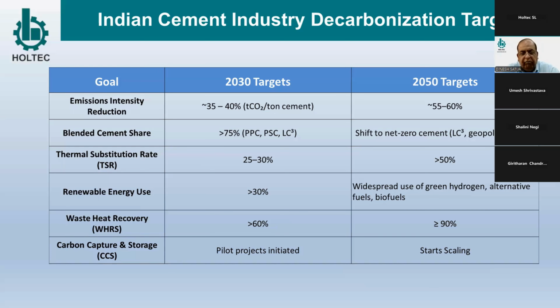TSR, if we talk, 25 to 30% by 2030 and more than 50% by 2050. Renewable energy use more than 30%. And in 2050, we foresee widespread use of green hydrogen, alternate fuel, biomass, no fossil fuel. Waste heat recovery more than 60% in 2030 and more than 90% by 2050, 90% of the potential. Carbon capture and storage, as per the projection, by 2030 we could see pilot projects initiated. By 2050, we'll see that pilot projects are converting into commercial production and bigger size units. So we can foresee that in the coming years, maybe after 5, 10 years, carbon capture will also be realized on the ground in India.